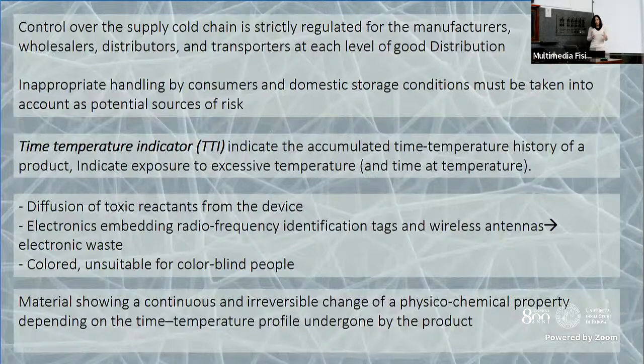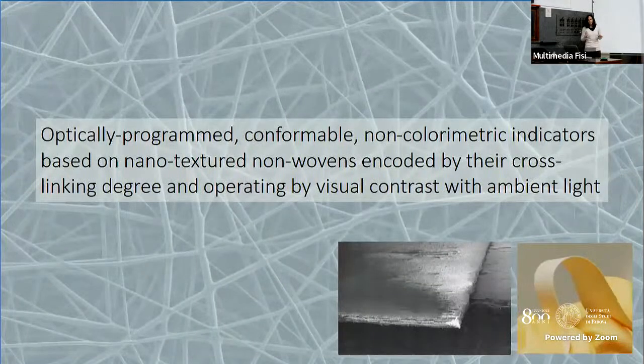You need a material which shows a continuous and irreversible change of some physico-chemical properties. And this change must depend on the time temperature profile undergone by the product. So what we did was to make an optically programmable, conformable, non-colorimetric indicator, which was based on nanofibers, non-woven web, that are encoded by the cross-linking degree of the fibers. And these devices operate by visual contrast, so you just see the difference by eye.